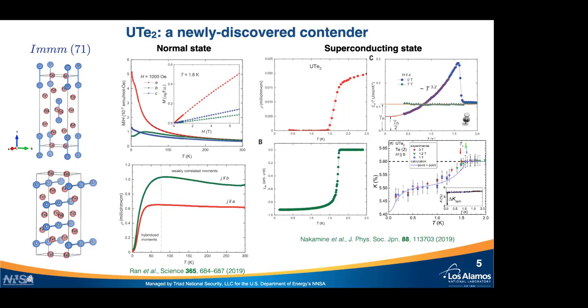and these here are newer results on single crystals, and they do see a small drop in the Knight shift at TC, but again, it's a very small drop. It doesn't go to zero. It's consistent with a spin triplet superconductor with the so-called d vector of the superconducting order parameter pointing along the B axis.